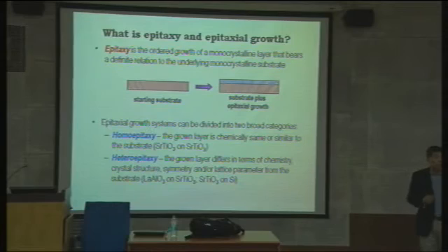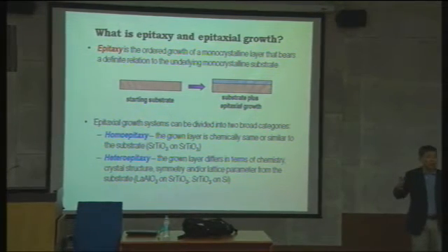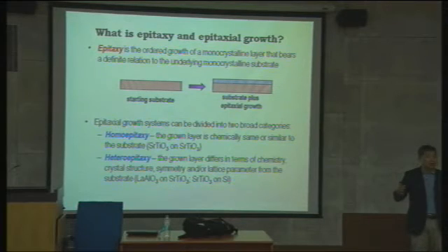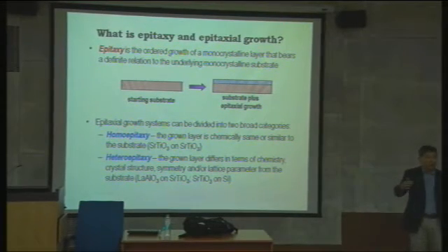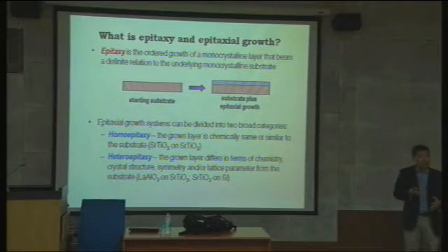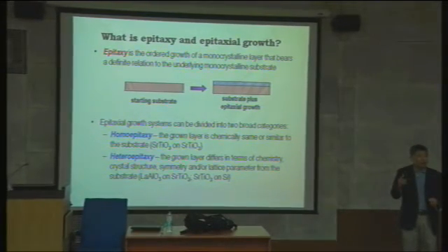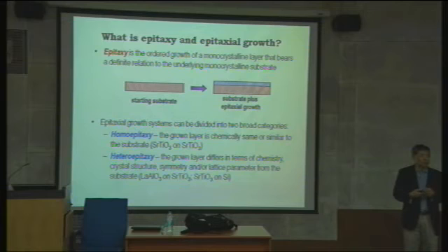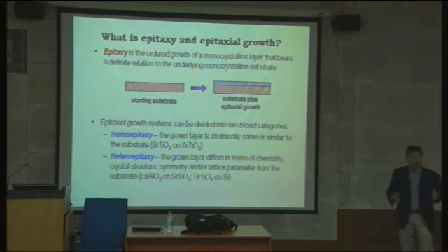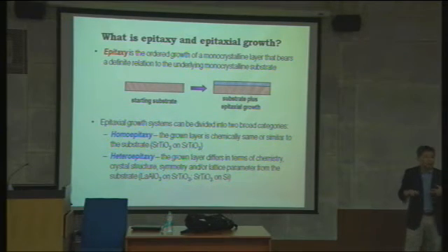But it grows beautifully, epitaxially. How can you have such a large lattice mismatch and still grow epitaxially? The way it grows, it rotates 45 degrees. When you rotate 45 degrees, the half diagonal, 5.4 angstrom divided by the square root of 2, is roughly the lattice parameter of the perovskite. So you can match it, not perfectly cube on cube, but sometimes by rotating 45 degrees. That's a lot of interesting epitaxy. Sometimes it's unimaginable: oh, this can grow on top of this.